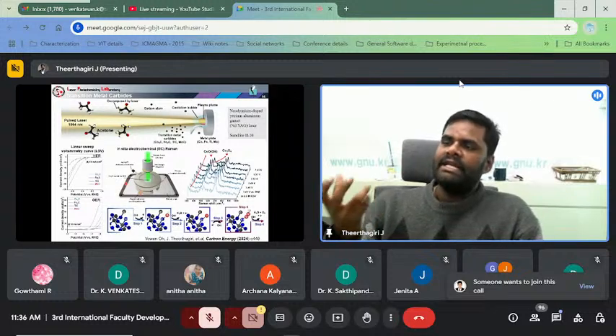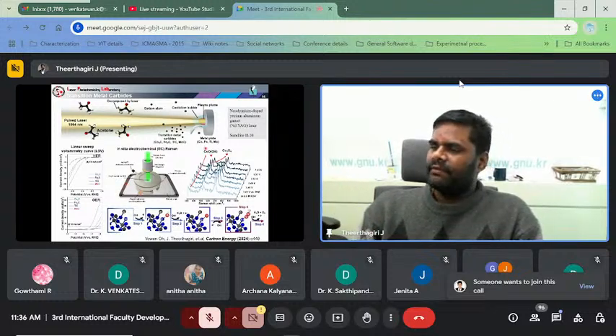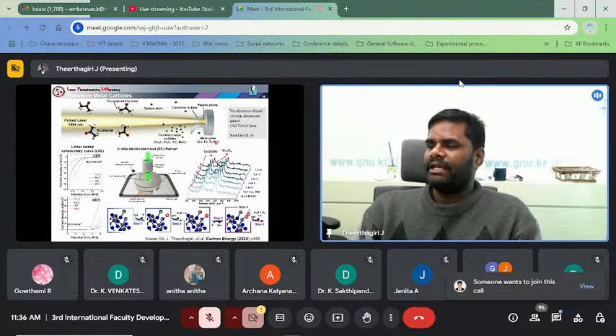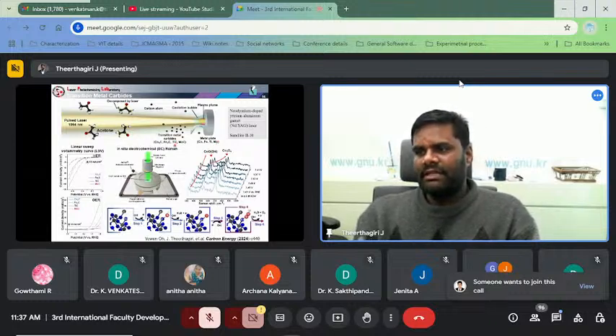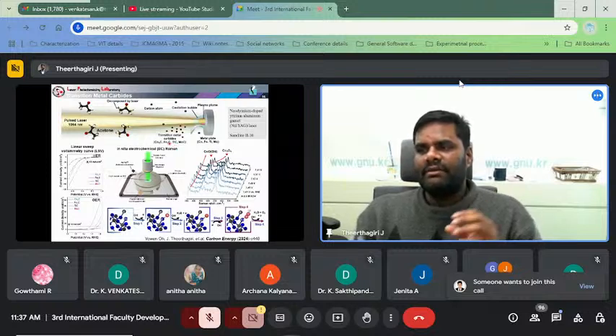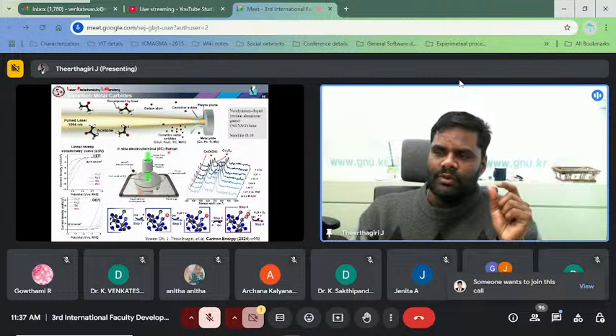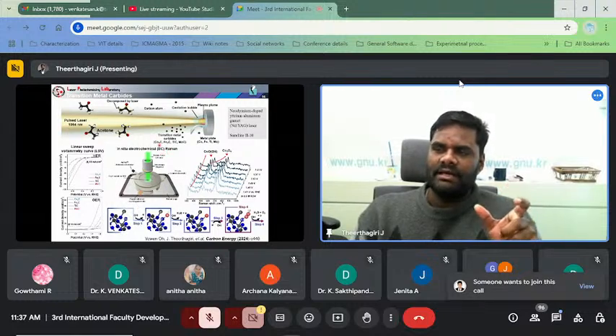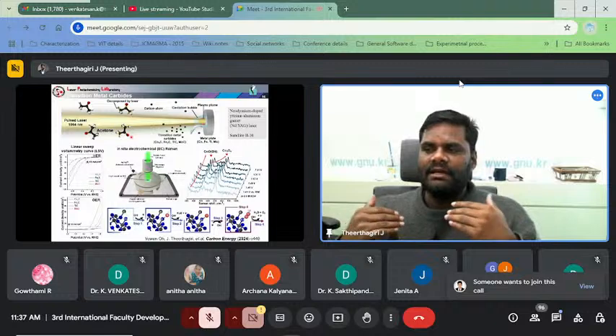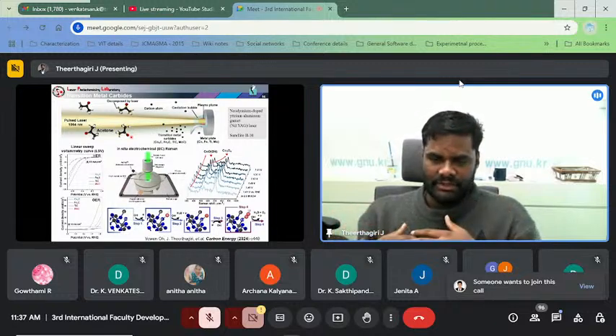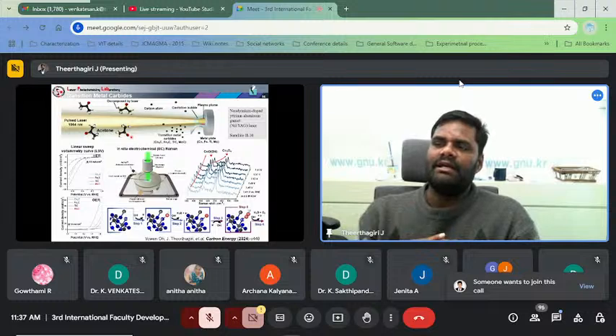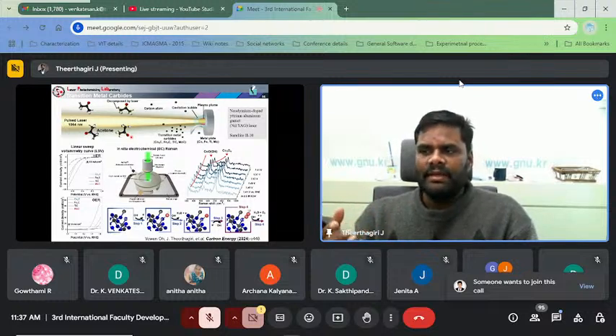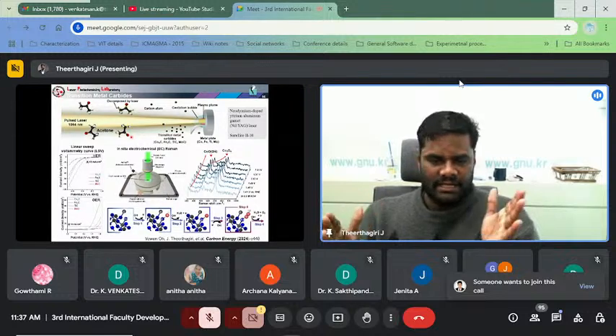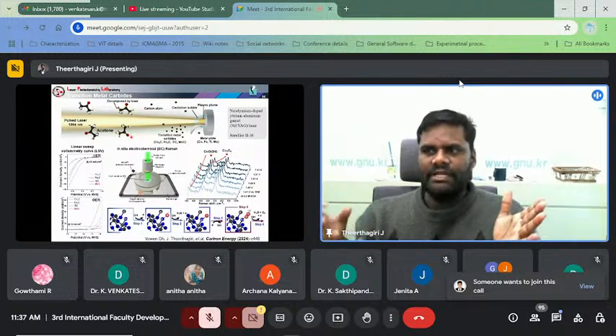What we did in this work is we took various metal plates, cobalt, iron, titanium, molybdenum, and converted them into the corresponding metal carbides. With this technique, within 10 minutes, we can produce the pure phase of carbides in acetone solvent without any external carbon sources. Generally, typical metal carbide synthesis takes place by high temperature programmed reactions, like gas and solid phase reactions. For example, with gas, we use methane gas.